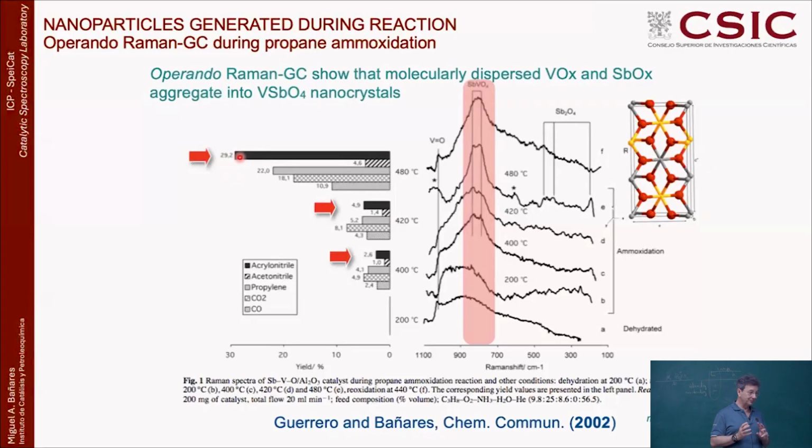So if you go to the patent of the original vanadium antimonate catalyst, pure vanadium antimonate without any promoter, any additive or anything, but just the basic vanadium antimonate, those patents are reporting 30% yield to acrylonitrile. Now here, this catalyst is affording 30% acrylonitrile. So, well, that's nice. It is performing like the patents of the basic vanadium antimonate catalyst, but there is one very important difference. Those patents are using 100% vanadium antimonate, and here we have one monolayer, like 90+% of the sample is alumina, inexpensive, economic, and only a little bit is vanadium antimonate, but that little bit is all you need.